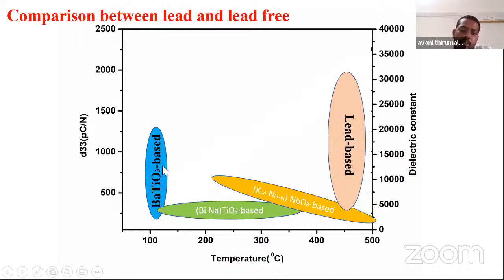The BaTiO3-based materials have very low transition temperatures compared to other materials. These bismuth sodium titanates have low D33 and low dielectric constant, but the transition temperature is in between the lead-based and lead-free materials. The sodium niobates and sodium potassium niobates have a somewhat better D33, and the transition temperature is very high compared to all the materials. Depending upon the application, they will choose which material is suitable. But normally, lead-based materials play a major role in devices, due to the high dielectric constant, high D33, and high transition temperature.